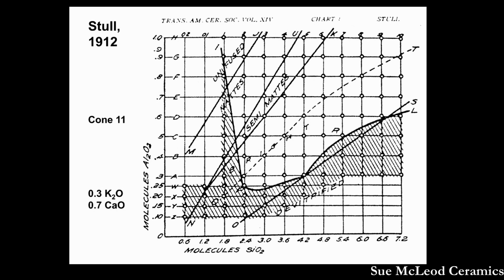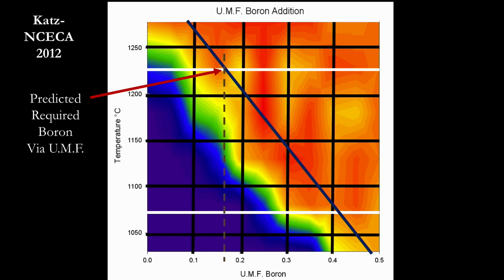Stull's research was done at cone 11. For my research project, I recreated Stull's map at cone 6 to see if the same patterns would exist at a lower temperature. Since I was working at cone 6, I couldn't rely on the fluxes alone to sufficiently melt my glazes. I needed to include some boron, which is a low-temperature glass former. This chart, written by Matt Katz, shows the relationship between boron levels and firing temperature. Based on this data, a consistent boron level of 0.15 was chosen for all of my tests, which is the ideal level for cone 6.